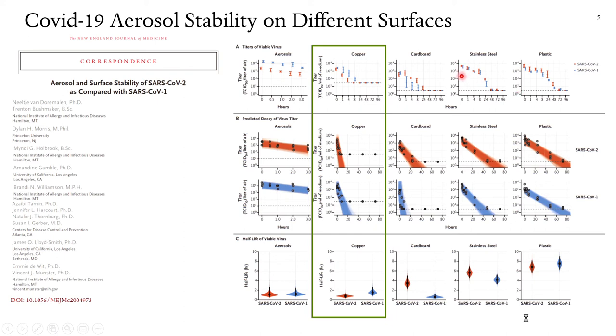And the data showed that the viruses, especially COVID-19, live the longest amount of time on stainless steel and plastic, while the shortest amount of time on copper and cardboard is in between. So on copper, no viable COVID-19 was measured after four hours.